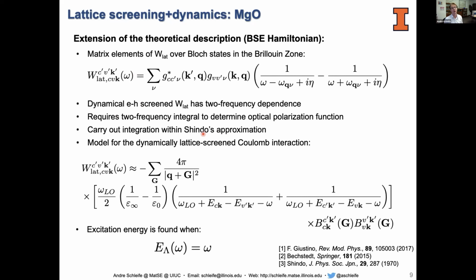That's again known in the literature for many years, and we express the model function for a dynamically lattice screened Coulomb interaction using a Fröhlich model. So that's what you can see here. That's the final expression that we then implemented. Once this is frequency dependent, it's not sufficient to diagonalize only one excitonic Hamiltonian anymore. Now you need to diagonalize multiple, and you need to find the excitation energies that fulfill this relation simply because of this frequency dependence.